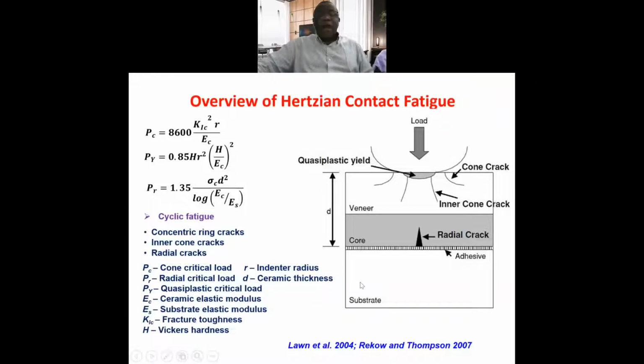So in the literature, these are the parameters you can use to get the maximum load for cone cracking, maximum load for plastic yield, maximum load to initiate radial crack. So this one, the critical load for the cone crack, is a relationship between the fracture toughness, radius of the indenter, and the ceramic modulus.